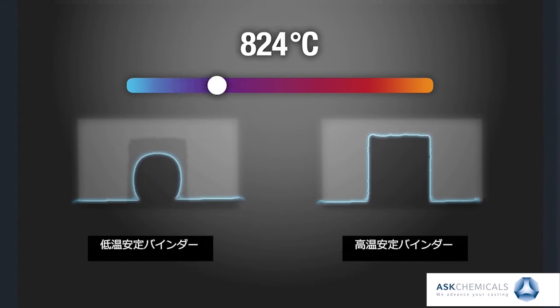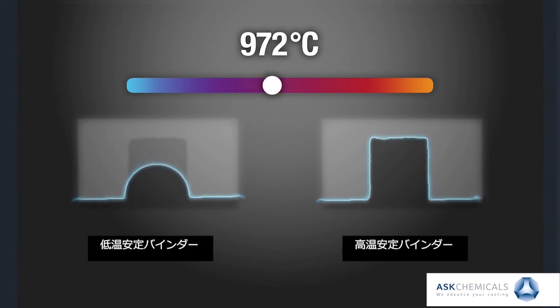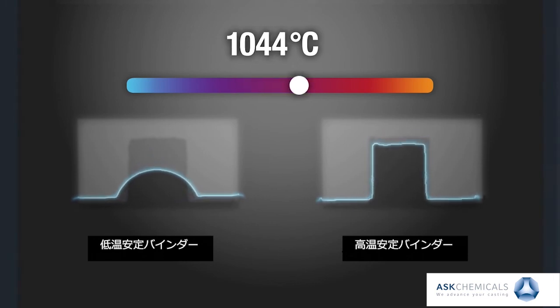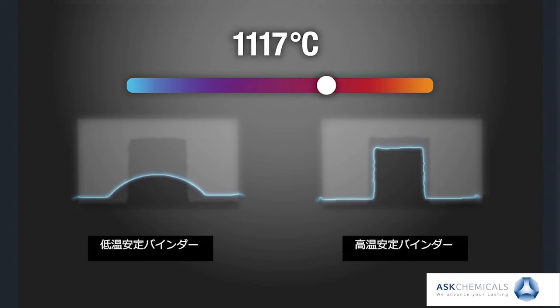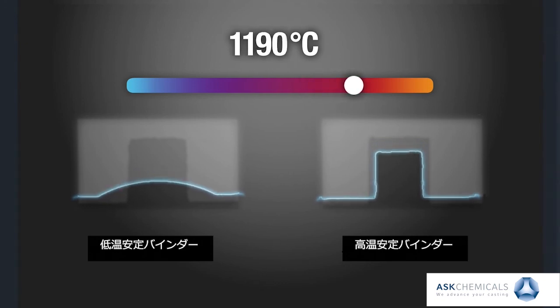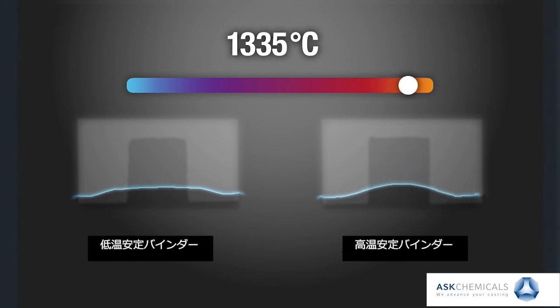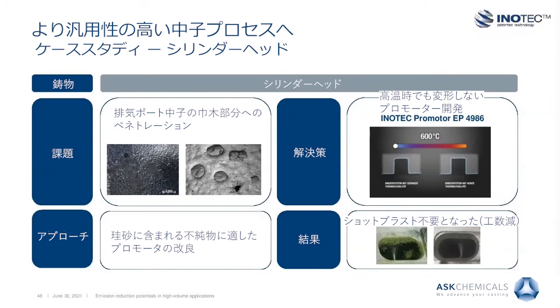The specimen on the left here shows a low thermal stability and softens at temperatures below 730 degrees, the casting temperature of aluminum melts. The sample on the right exhibits a high thermal stability and softens outside the temperature range of aluminum casting applications, and the specimen remains stable over a wide temperature profile. The result of customizing the thermal stability of the binder system to the impurities of the local sand quality is that the defect of penetrations disappears, removing the need for cost-intensive shot blasting.